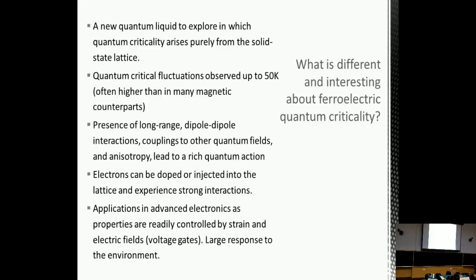So what's different and interesting about ferroelectric quantum criticality? Well, it's a new quantum liquid to explore, in which quantum criticality is arising purely from the solid state lattice. It's not coming from electron charges or spin degrees of freedom. Quantum critical fluctuations have been observed up to 50 Kelvin or more, which is often quite a bit higher than in electronic systems. Ferroelectrics have not only short-range interactions, but long-range dipole-dipole interactions. And usually coupling to the lattice strain is important. So that can lead to quite a rich quantum action and a rich phase diagram.